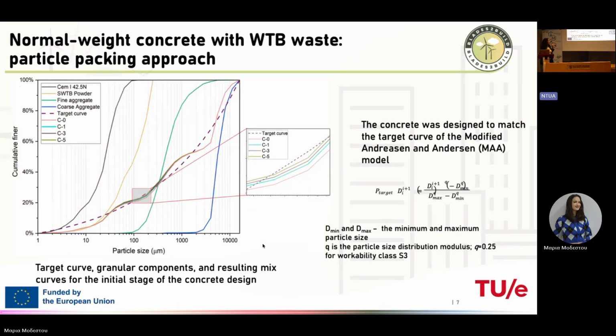So this is the particle size distribution of all the components we used. We used traditional natural sand, rather fine sand, traditional coarse aggregate, gravel, so all common traditional materials for the Netherlands. We used cement, and since we have many components, the most important is the calculation of the mix design.